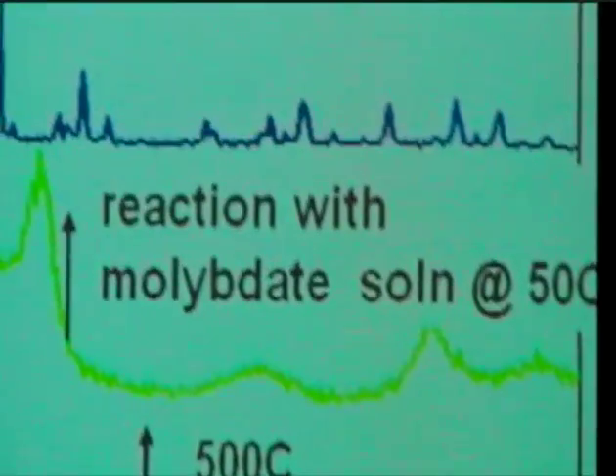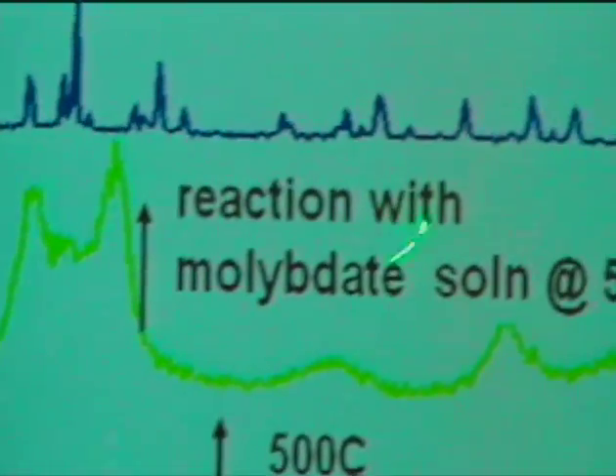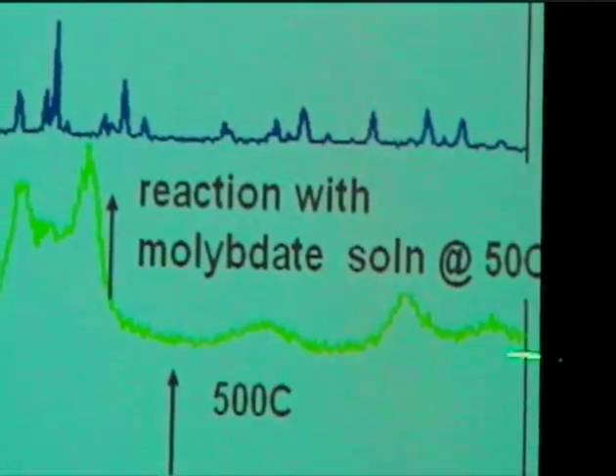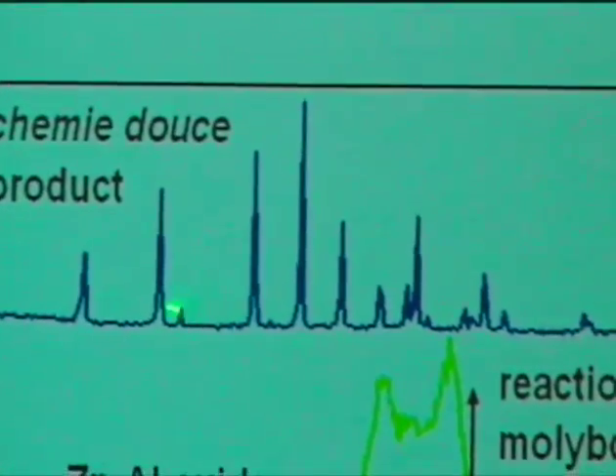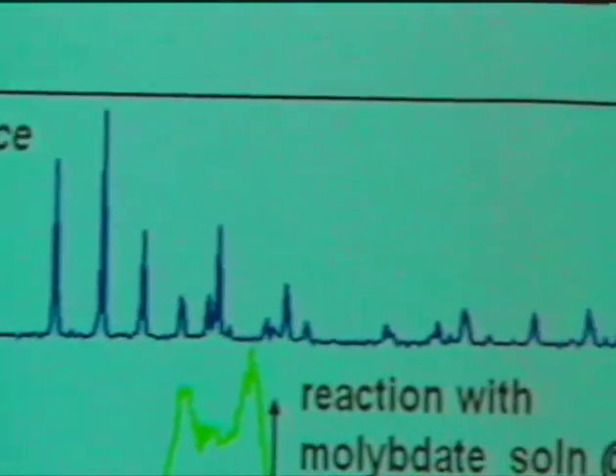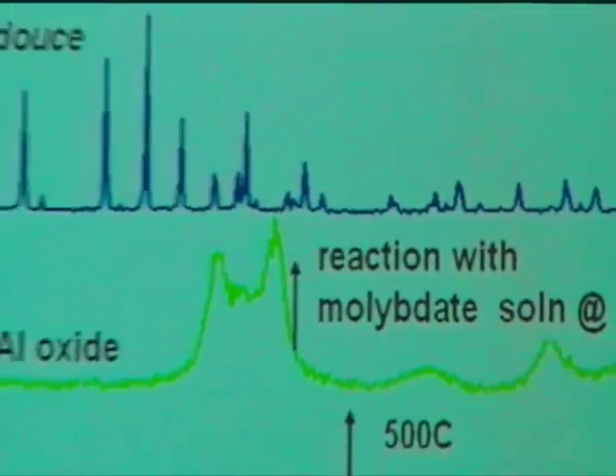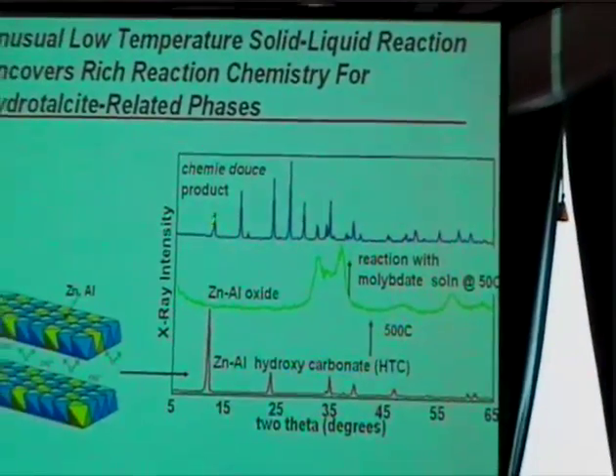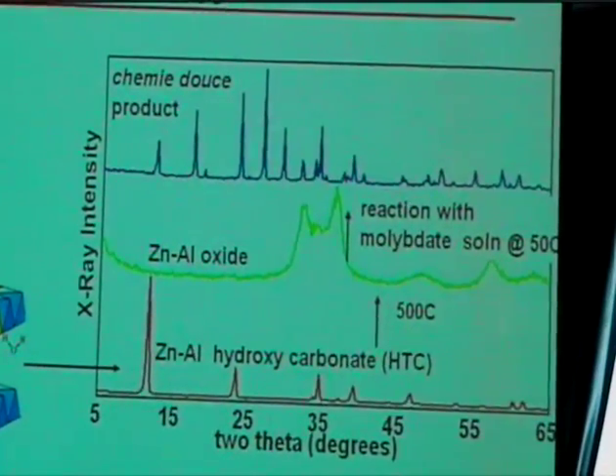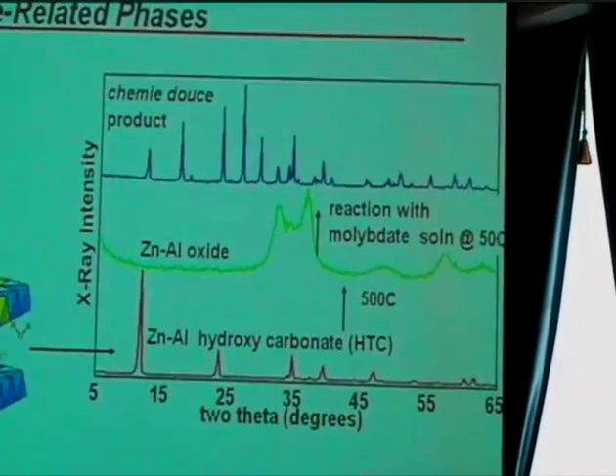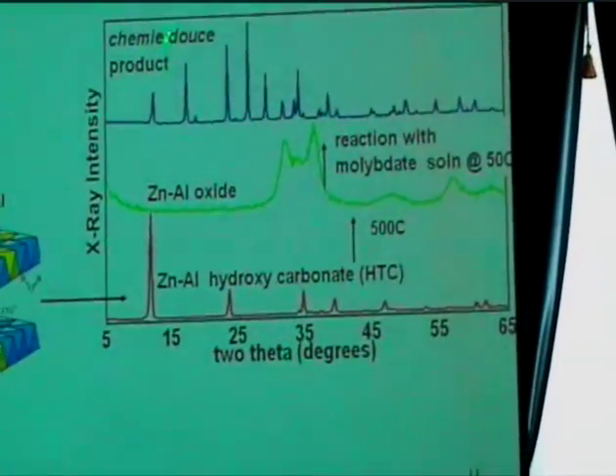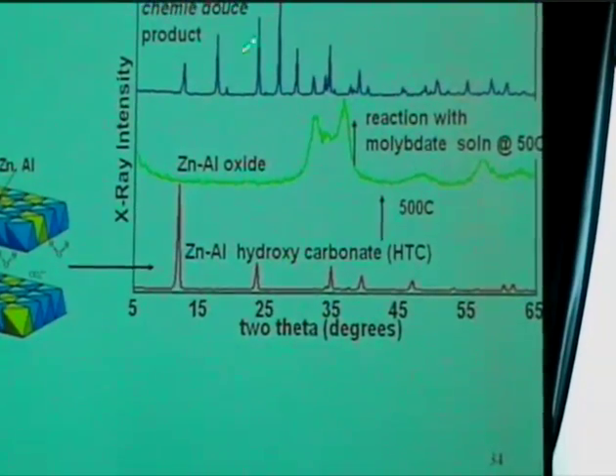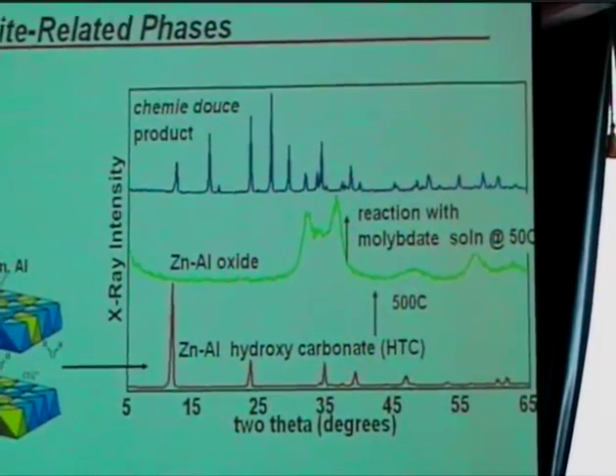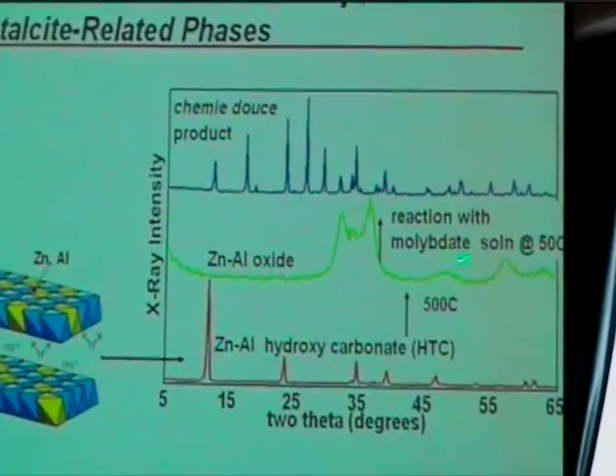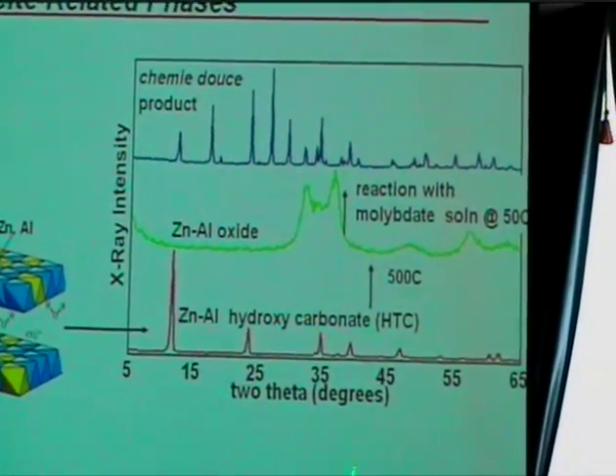The interesting part came when we took a solution, simply a solution of ammonium molybdate, and put it into a suspension of this oxide at 50 degrees C and let it sit there for about an hour. Well, we took the solid that came out, and we wound up with something that looked like this. It had changed. Now, you might look at this top pattern and the bottom pattern, and there is perhaps some relationship there, but it is clearly different from what we went in with. So this was fascinating, and it looked like there was, in fact, what we call a chimie douce reaction, a low-temperature, soft chemical reaction, converting these hydrotalcites to something which looked like it might have had molybdate associated with it.